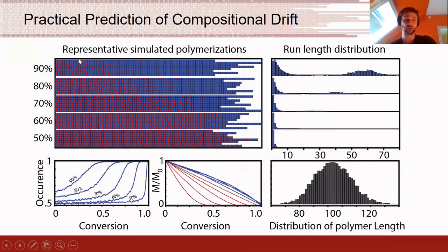If you have 10% monomer, it's consumed fairly early on. You take it up to 50-50. In this particular one, as you would expect, in an alternating copolymerization with a 50-50, it's alternating pretty much all throughout. And these are the lines that were in the first diagram before, the second one shown, and we've built in a crude way of implementing the dispersity index in the copolymerization. So you can change how effectively your RAFT agent works in it, and this will give you different dispersity indexes. So it can give you an idea of whether you have a pretty polymer or not and what that actually means.